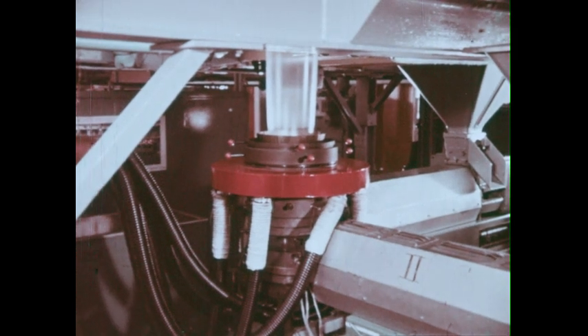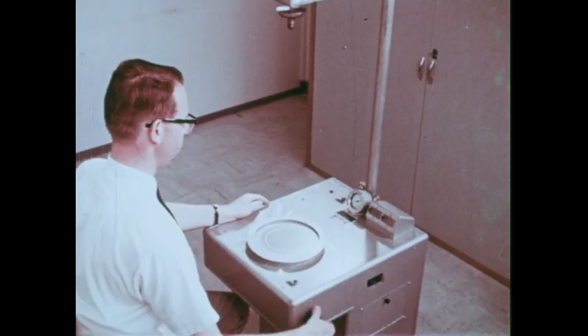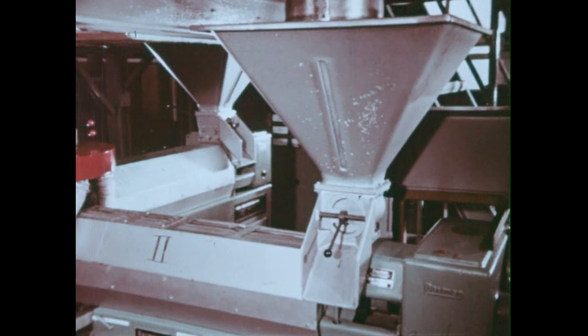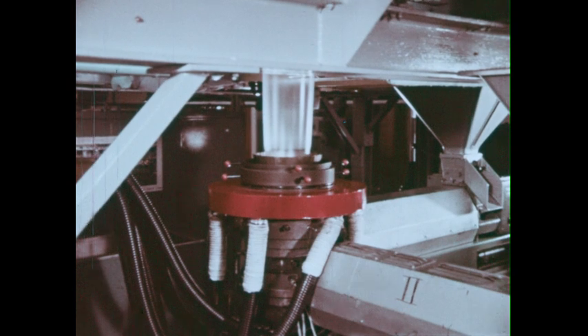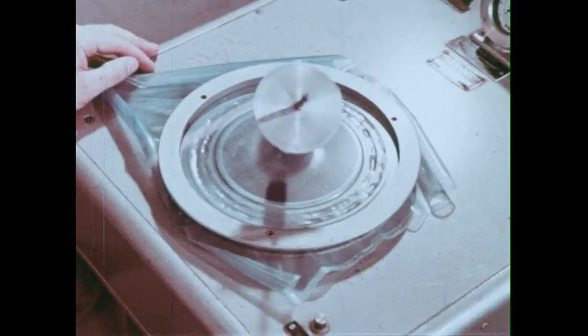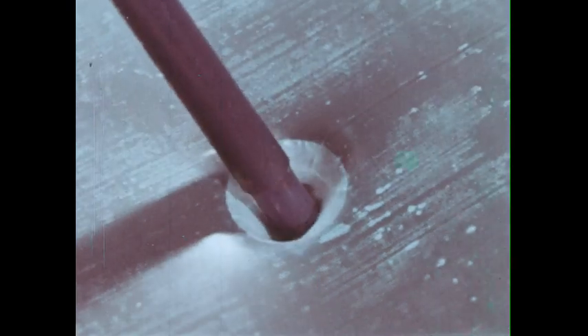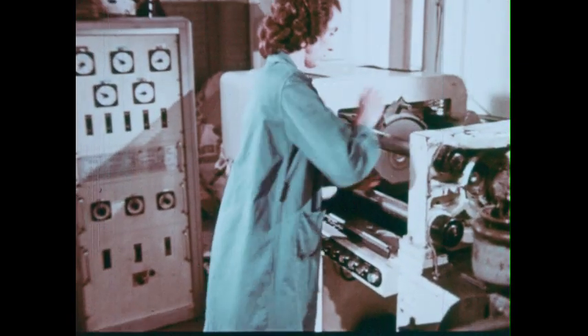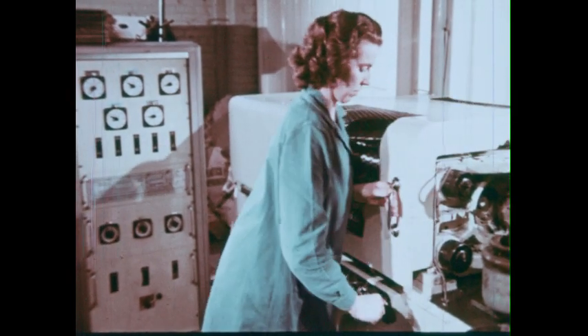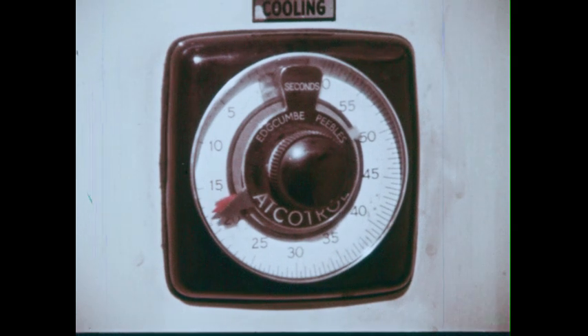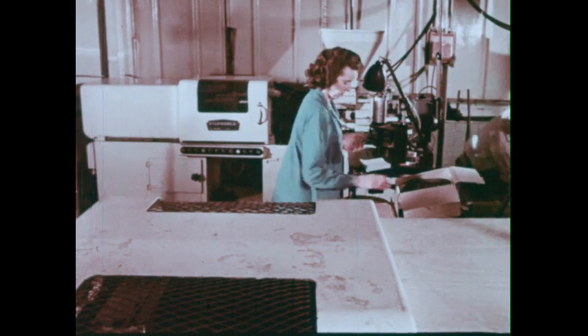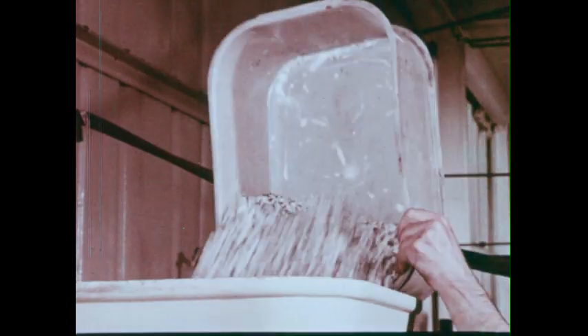This is polyethylene film for packaging. One disadvantage: its low resistance to impact. By using two extruders together, we can coat the polyethylene with a layer of thermoplastic rubber. And this makes all the difference. Thermoplastic rubber has already found many commercial uses. For these turntable mats, it means improved quality and fewer rejects. Above all, no time spent on vulcanization. Any scrap or waste can be ground up and used again.